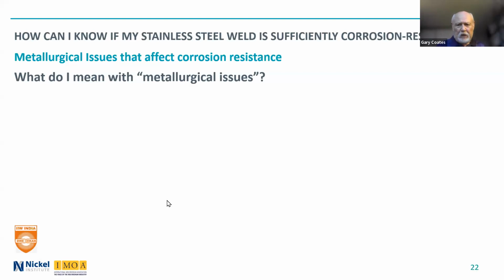And how to remove the chromium depleted layer. Pickling will actually remove it. I did forget to mention that. If you use the proper pickling liquids, and I say that most pickling liquids and pastes are designed for 304, 316 material. When you get into the higher molybdenum, the more corrosion resistant materials, the duplex materials, they will not be as effective, and sometimes you have to beef up the hydrofluoric acid content, is usually what they do, or reduce the nitric content, and that will remove it, as well as grinding. But the pickling method is really the best way.